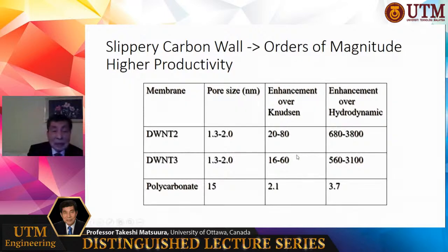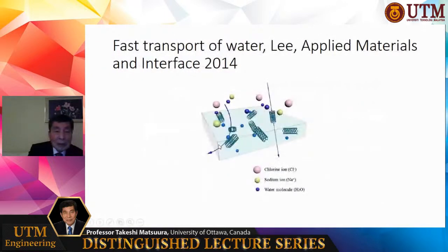Therefore, it has given hope that we can improve the flux or productivity of the membrane tremendously at that time. But industrially, it is very difficult to make the practical membrane. Therefore, it hasn't been commercialized yet. Instead, people attempted to incorporate nanoparticle into the polymeric thin layer, polyamide thin layer, and to use it commercially, to use it industrially. And indeed, by this method, the flux has increased, but not as much as it was expected by the carbon nanotube membrane.